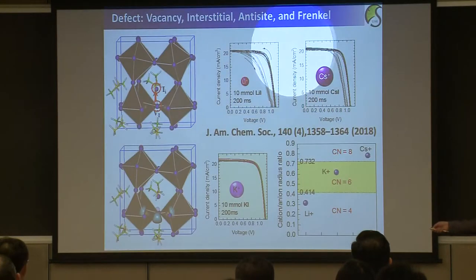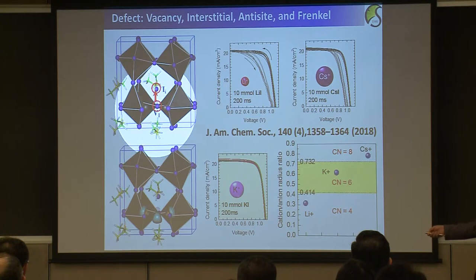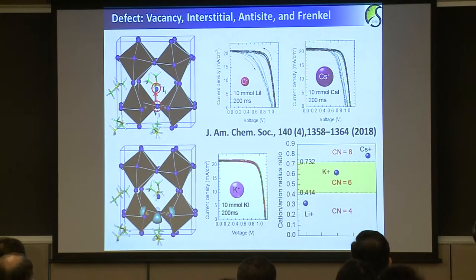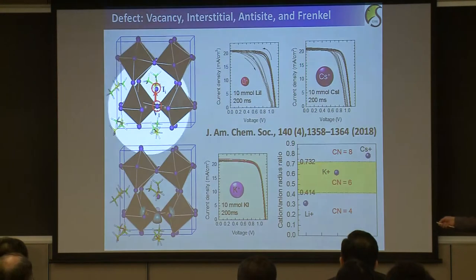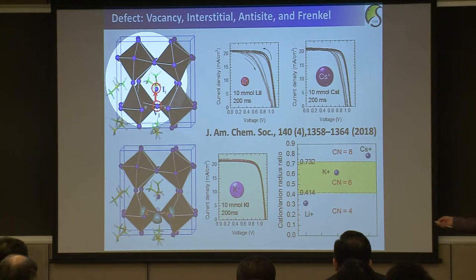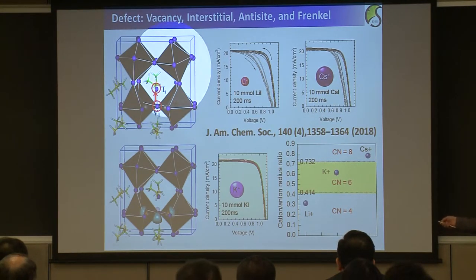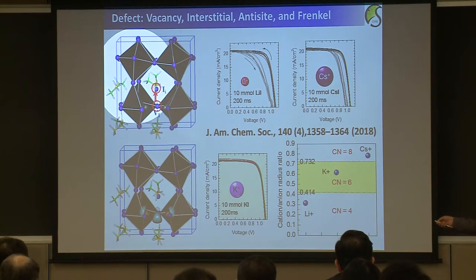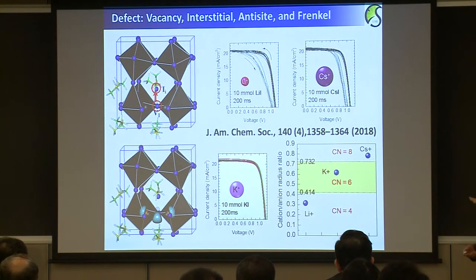So Frenkel defect meaning that you have the iodide here, and then the iodide is moving toward the interstitial site, and then you have the Pb-Pb dimer structure, which is pretty much stable in terms of energy. And then, for instance, here interstitial site in the vacant site, probably the A site, if you add some ion, such as potassium ion, then you can inhibit the migration of the iodide into the interstitial site. So you can inhibit the Frenkel defect.